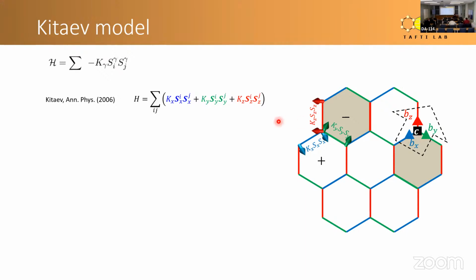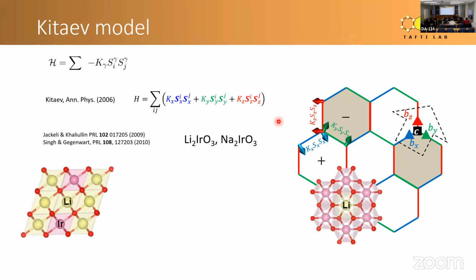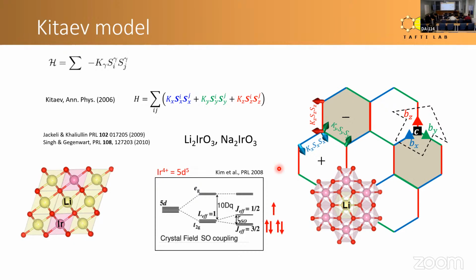So there has been plenty of interest in realizing that model. And the realization of that model in terms of materials started with pivotal theoretical work by Jackeli and Khaliullin back in the early 2010s, where they proposed that 5d iridium oxide materials with a honeycomb lattice, namely lithium iridate and sodium iridate, could be the realization of this model. In these materials, you have iridium atoms on the vertices of the honeycomb lattice. Lithium atom sits at the center of the honeycomb. And because of the strong spin-orbit coupling of iridium, there is hope for bond-directional anisotropic magnetic interactions. And also, the Kitaev model is a model for spin-half particles. Here, also, you can have a spin-half, not in the sense that you have S equal to half, but you will have a J equal to half.